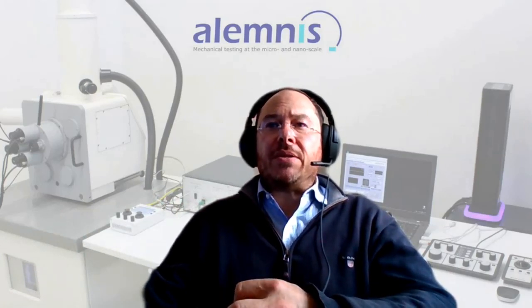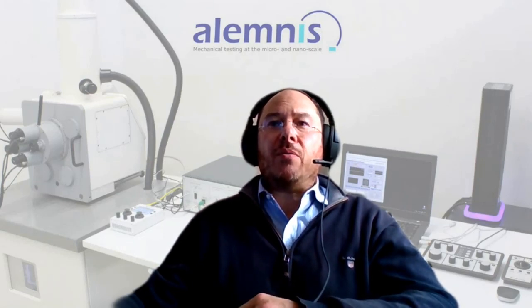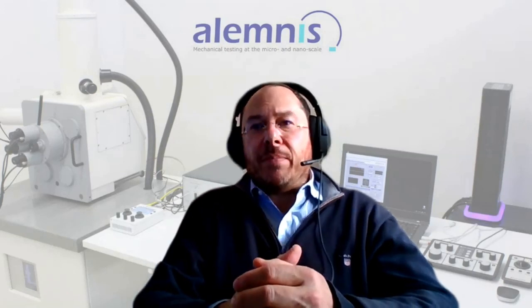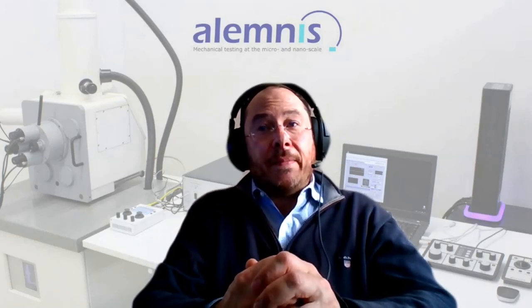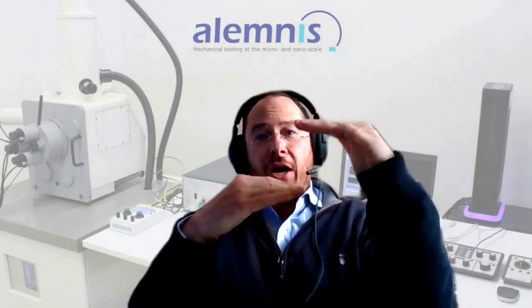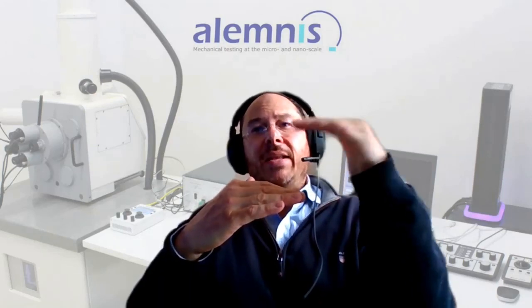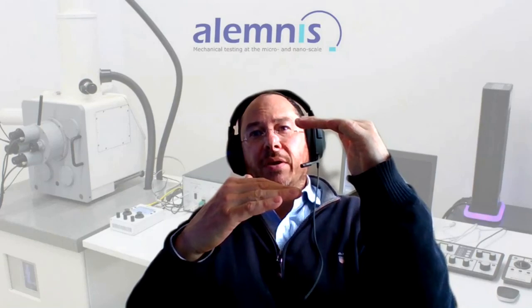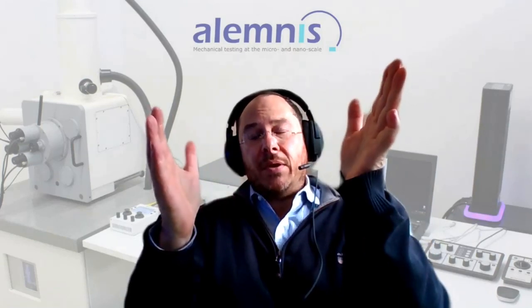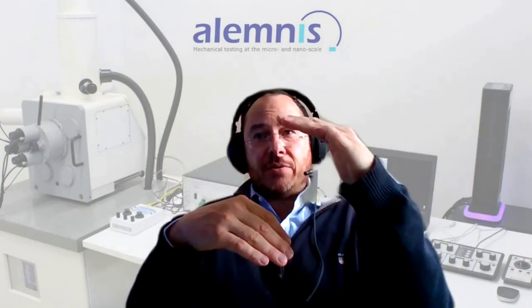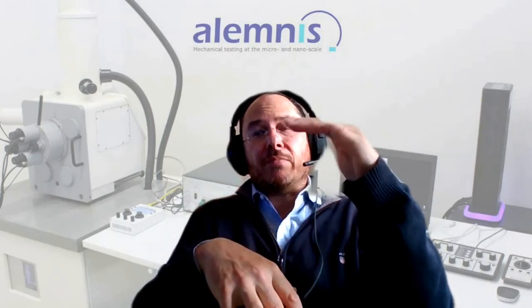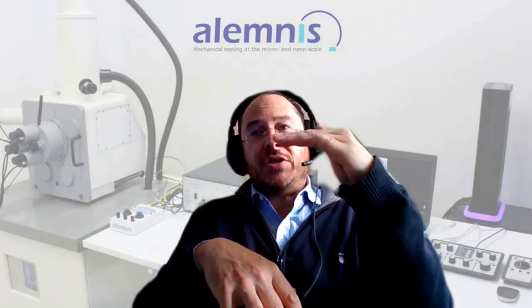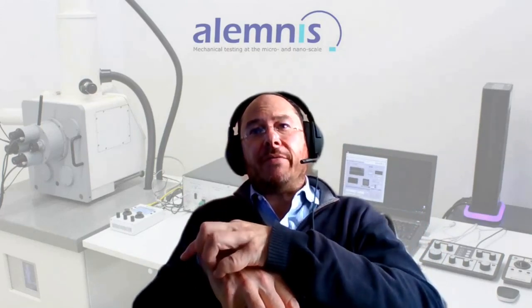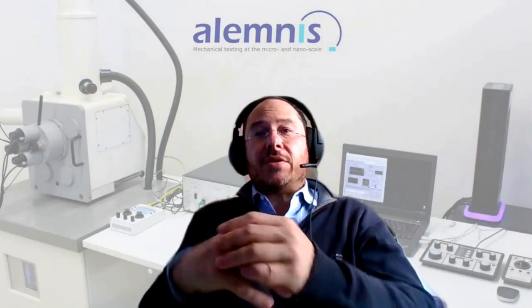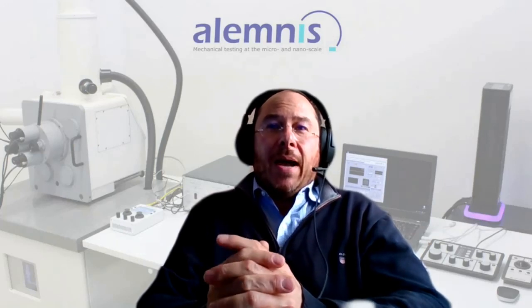There's another question here. Please explain the depth limit of coating for determining hardness without pileup. So this really depends on the type of coating that you have. If you have a soft material on a hard substrate, then any depth of indentation is probably going to cause quite a lot of pileup. If you have the opposite, let's say a hard coating on a soft substrate, then you can probably go relatively much deeper into the coating without having the pileup effect. So this question is really application specific.